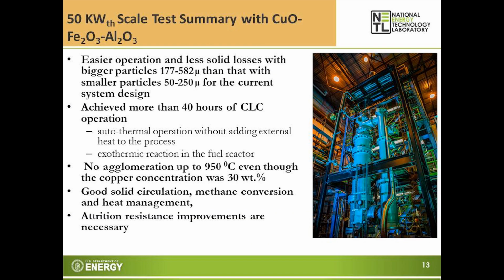So this is a summary of the 50 kilowatt thermal scale test with the copper, iron, alumina oxygen carriers. We saw easier operation and less solid losses with the bigger particles, that's 177 to 582 micron, than with the smaller particles for this current system design. Now, we achieved more than 40 hours of chemical looping combustion operation. That means we can get autothermal operation without adding external heat to the process. And for this size pilot scale unit, this was possible because of the exothermic reaction in the fuel reactor. We didn't have to carry heat. And we didn't see any agglomeration of the particles. We operated up to 950 C, even though the copper concentration was 30 wt.%, which is very high. We saw good solid circulation, methane conversion, and good heat management. And we did see some solid losses, so our next goal is to improve the attrition resistance of the material further.